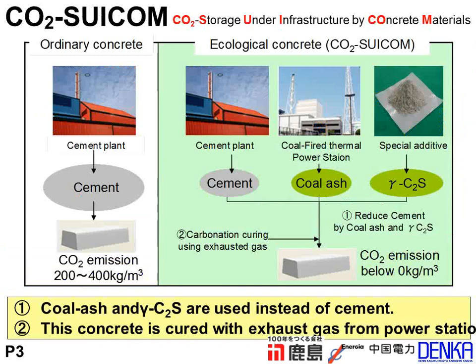This concrete is named CO2-SUICOM. This is an abbreviation for carbon dioxide storage under infrastructure by concrete materials. The amount of carbon dioxide emission of ordinary concrete is 200 to 400 kilograms per cubic meter. But for this new ecological concrete, below 0 kilograms per cubic meter is the fundamental concept.